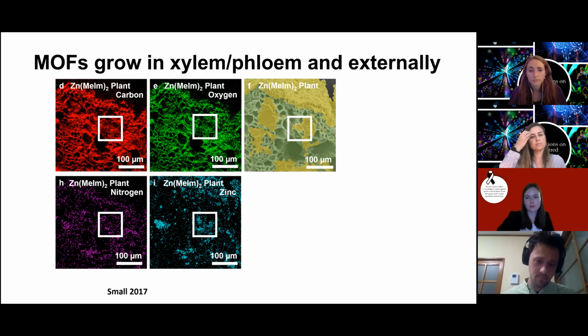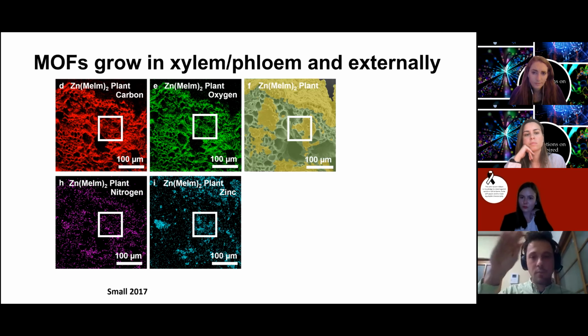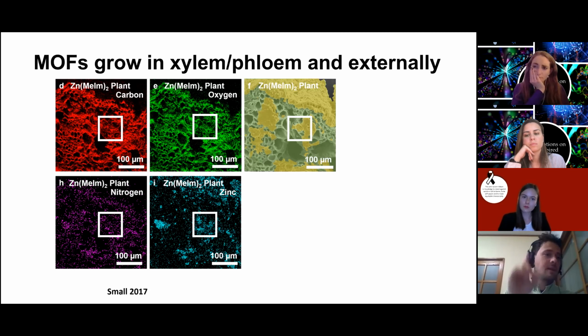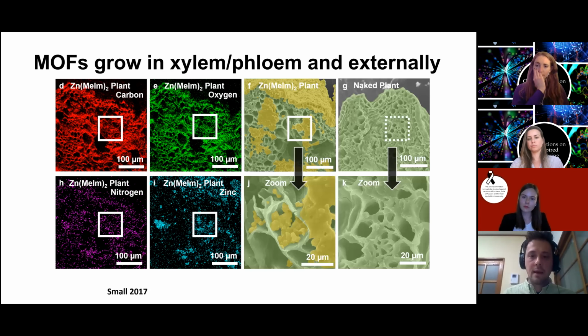So this is my favorite picture from all of them. This is essentially SEM, a cross section, and we have the elemental mapping there. The zinc is only from the MOF, and the nitrogen, of course, and the oxygen and the carbon are mixed. The oxygen is just from the plant, but the carbon and the nitrogen come from both the MOF and the plant itself. If we look at the false color, that's where you really see all these crystals everywhere. And you see them on the outside of the plant, which is that top part, and then you see them in the xylem, not as much in the phloem, which really shows that this is happening as the materials are being taken up. If we compare that to a naked plant, you can see the naked plant is very, very smooth.